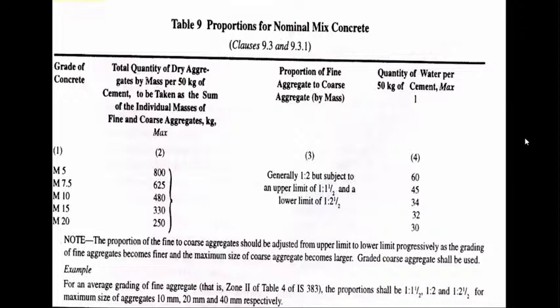So when your aggregate becomes larger, you are supposed to go down, which means when your aggregate is the smallest, you are supposed to go up. So when you have a 10 mm aggregate, then you should use a ratio of 1:1.5. When you have a coarse aggregate of 20 mm size, you are supposed to use the ratio of 1:2. When you have an aggregate size of 40 mm, then you are supposed to use the ratio of 1:2.5. Okay, I know it will be a bit confusing as of now, but it will be easy for you when we do an exercise.